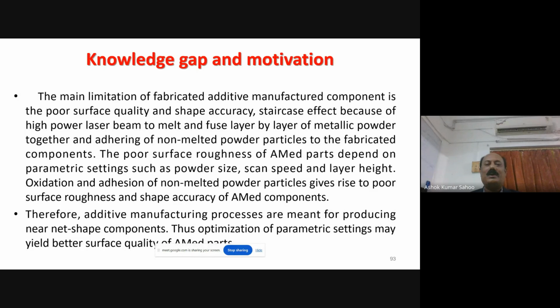The main limitation of additive manufactured parts is the poor surface quality and shape accuracy, the staircase effect, because a high power laser beam melts and fuses metallic powder layer by layer, and non-melted powder particles adhere to the fabricated components.